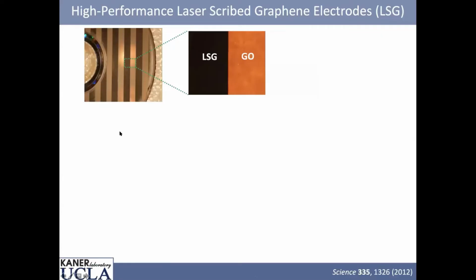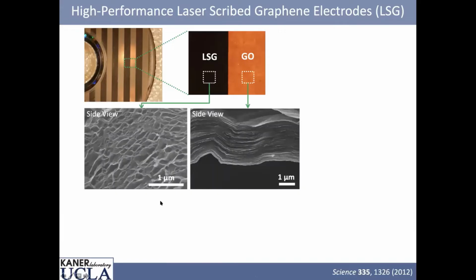So if I haven't gotten your attention yet, this is the one slide you want to look at. So here we told the laser just to draw stripes. And so this cartoon is, we start with graphite oxide, we draw a stripe, laser scribe graphene. And here's what it looks like under a microscope. So graphite oxide is this beautiful layered compound. We hit it with a laser, it absorbs the light, it gets hot, it blows off CO2. And when we're done, we've created a fractal.